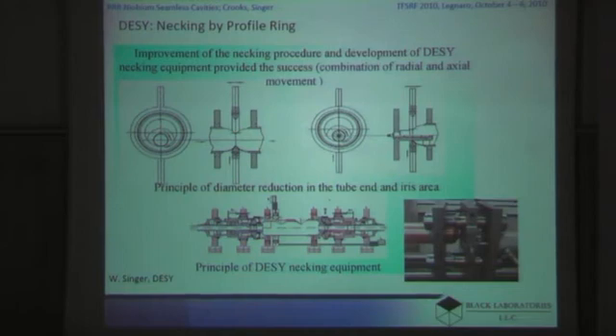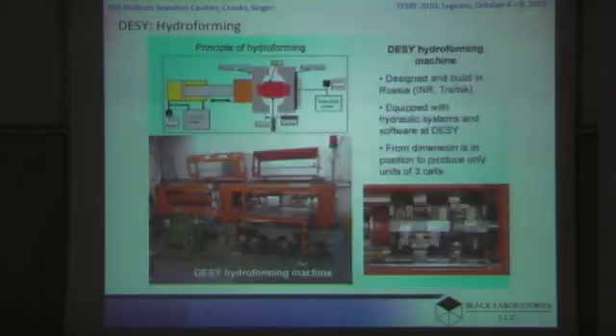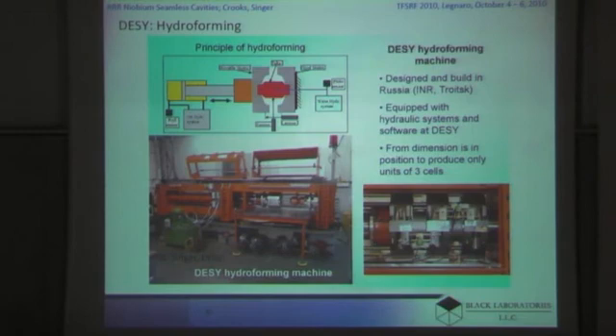The irises are produced at DESY by a necking process using spinning, or what they call profile ring spinning. The difference between that and other types of spinning, instead of using a small wheel on the outside, a large wheel in this mechanism here is used to apply pressure, and it's moved in both this direction towards the axis of the tube and in and out of the plane of the paper to provide the profile shape of the iris. After the irises are produced on the tube, it's then placed in a hydroforming device.